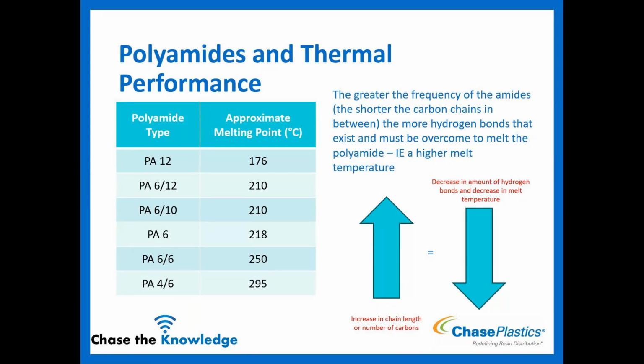So flip that. If I increase the chain length, so now I'm at a nylon 12 versus a 6, if I have more carbons in the backbone, longer chain, PA12, it equals a decrease in the amount of hydrogen bonds that exist, which equals a decrease in the melt temperature. So longer chains have lower melt points than shorter chain nylons do. And that data is provided here as well. So if you're at a nylon 12, which would be kind of the longest ones we tend to see or work with, it has a melt point of 176 C, then I drop down to a 6.6 and it jumps all the way up to 250 degrees C. It's a pretty good swing. And then again, just 2 carbon difference to a PA4.6, it jumps another 45 degrees up to 295 degrees C melting temperature. So my longer chains pick up less moisture, but are lower heat than my shorter chain nylons are.